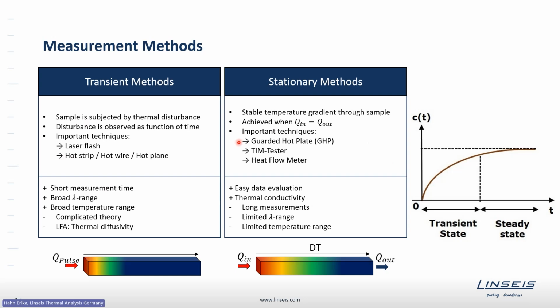The most well-known stationary methods are the so-called plate methods, to which the guarded hot plate technique belongs, the TIM tester, as well as the heat flow meter. The latter two we will have a closer look at later on as well. The benefit of the steady-state methods is that the data evaluation is very simple compared to the transient methods. You directly get the thermal conductivity based on the relation I showed before with the heat flow, the temperature gradient and the size of the sample. You can easily calculate that. Disadvantages are that the measurement time is quite long. Additionally, the thermal conductivity range is also limited, so mostly only moderately thermally conductive materials can be measured, and the temperature range is also more limited compared to the transient methods.